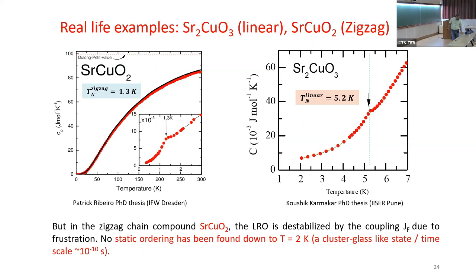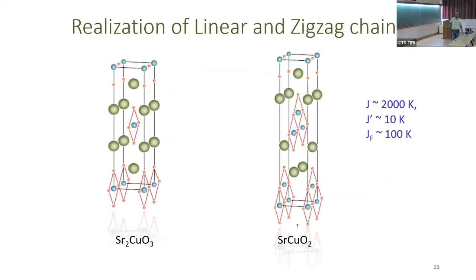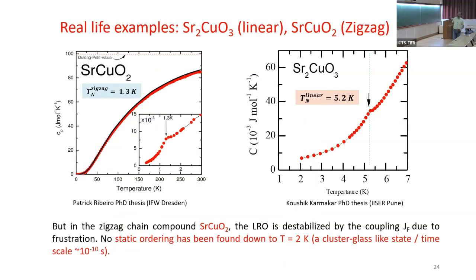Sorry, I didn't tell you that this one is strontium 2 copper oxygen 3, and this one is strontium copper oxygen 2. Now, if you want to look at the effect of frustration, by the way, I should also mention that these are the values of J, J prime, and JF for these systems. Here, of course, there's no JF. So you can see that in 112, which has the zigzag structure, the magnetic ordering has been suppressed down to a temperature of 1.3 Kelvin.